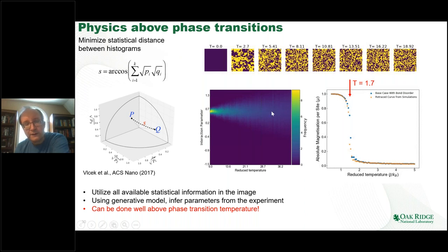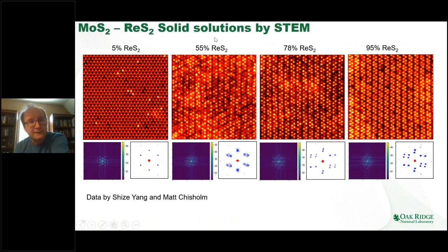What is really good is that this prediction is unbiased, meaning that if we have sufficient statistics, we still can learn the true physics of the system. Does it work experimentally? Well, this is the example. This is a solid solution of molybdenum sulfide and rhenium sulfide. If you have a very little bit of rhenium, you can see individual rhenium atoms, they're bright.